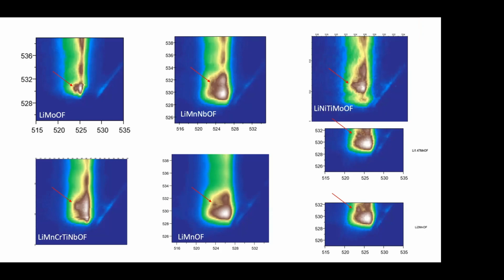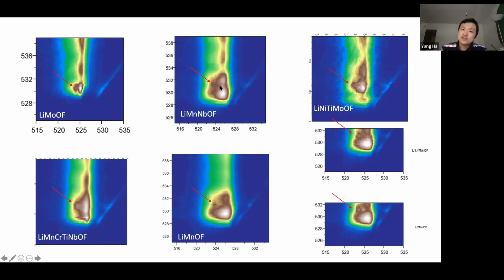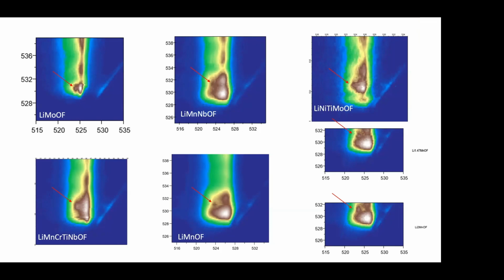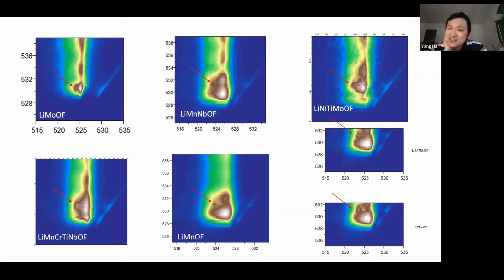I'm sorry, I will have to clarify. Do you think this feature is photo damage, or what is photo damage? I didn't get that part. Oh, this feature is not from damage, because we always do a photo damage test every time we start our experiment. So this feature is an oxidized oxygen. What I can tell is it's similar but looks different from the pure oxygen gas we had measured. If you ask me, I personally believe it's a peroxide species based on my own DFT calculations, but we still need more evidence to lock that in.